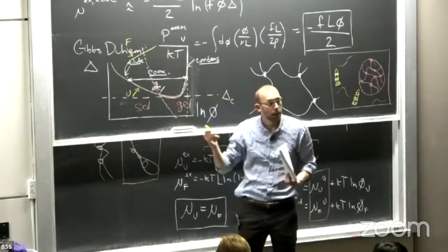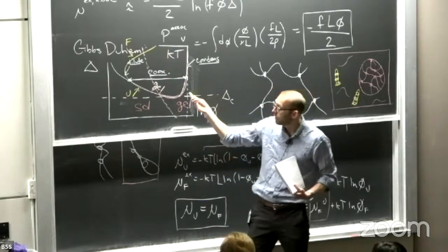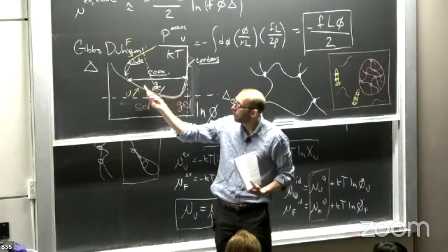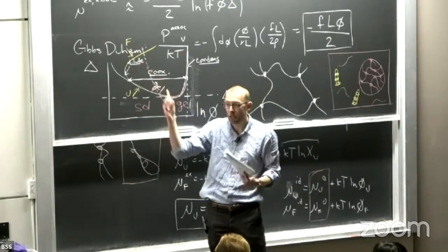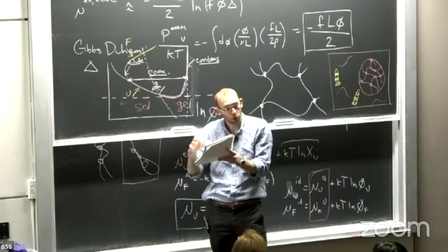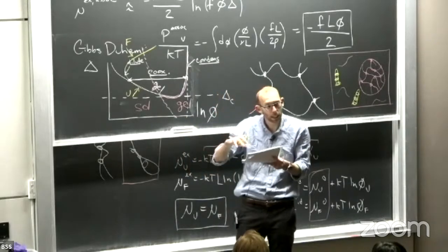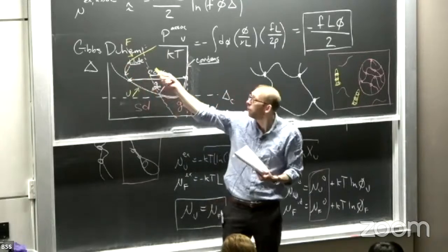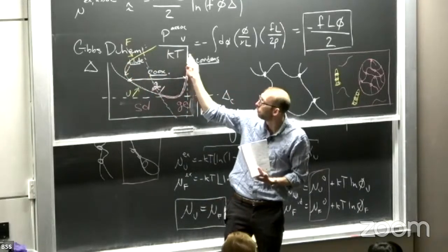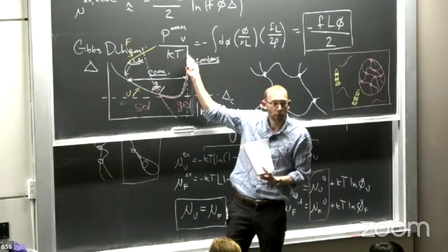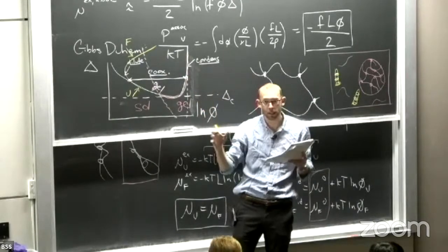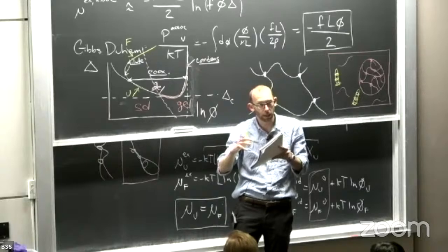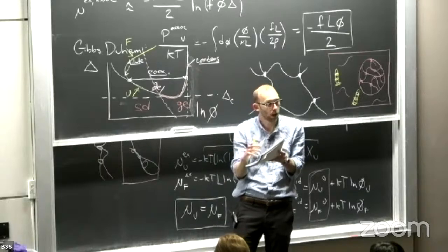So in this regime, the key thing is that you can see a competition between the formation of these small structures, say folded structures or small oligomers that are in your dilute phase, that oppose phase separation and tend to prevent the formation of these system spanning networks, because these bonds can be formed intramolecularly at a much lower entropic cost.